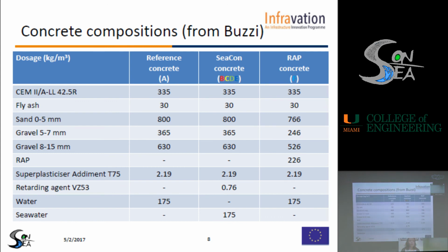So basically there are 3 different concretes: the reference concrete, the SEACON concrete that is the same as reference but contains seawater instead of fresh water, and finally the RAP concrete that contains, as I said, the partial replacement of recycled asphalt pavement that comes from the same plant of Pontenure where the demo project was located.